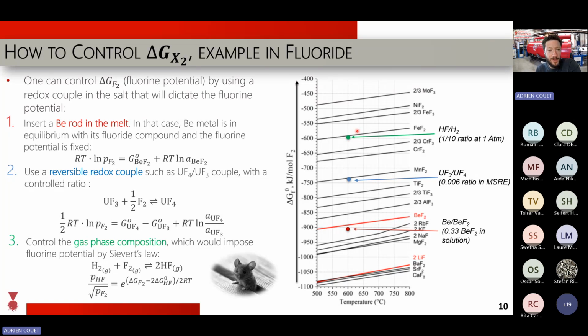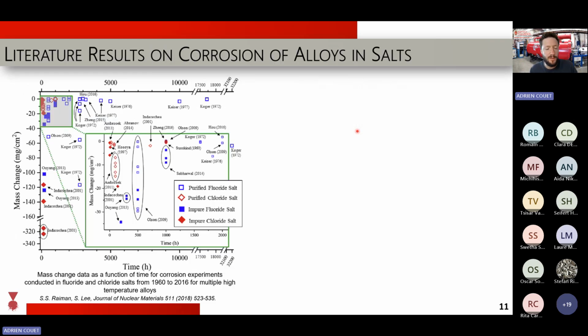Because actually, that would be way too easy, right? Controlling this redox buffer is extremely complicated. If you're familiar with PWR or LWR corrosion, there are very strict boundaries on the redox potential of water. We inject hydrogen gas to a very strict level to control that redox. And even so, we have corrosion issues in the core of the reactor, right? So even if you do the best you can with the chemistry, you're not going to get there, which means that you need to develop materials to also sustain corrosion.